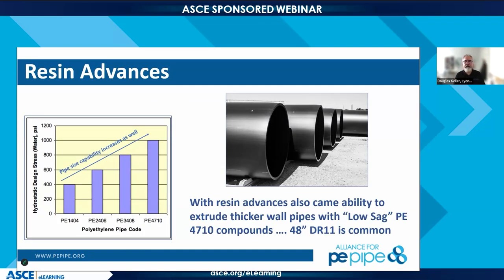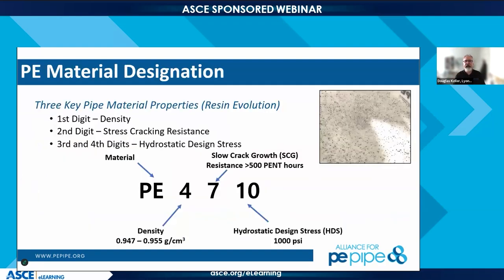If you could go back a slide, Alan. That 10 is 1,000 PSI, so that includes our design factor, and that's where we start when we start our design with the PE 4710 materials. We start at 1,000 PSI of tensile stress on the wall, and then we adjust that depending on pipe thickness and the applications that it's going into.